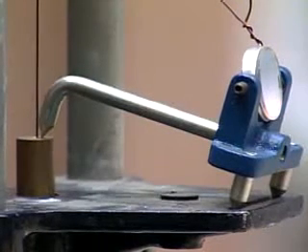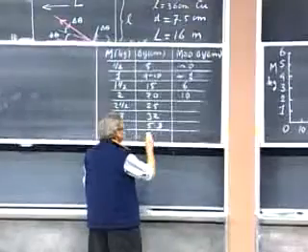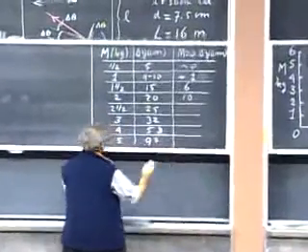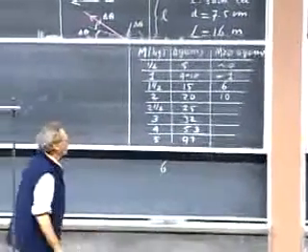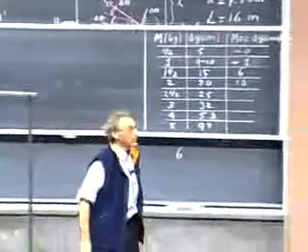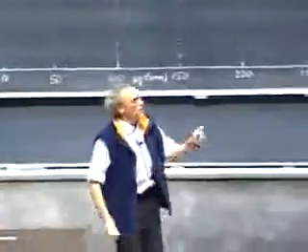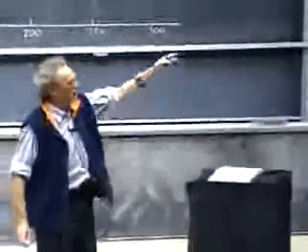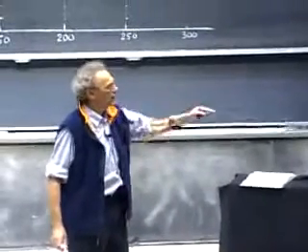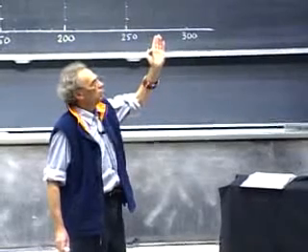Now you're clearly in that plastic flow portion. By adding 1 kilogram, look where that point is. It's still moving. What was 5? 97? So we're now at 6 kilograms. Oh, well, actually, that is still easy for me to estimate. I would say it's about double the length of that stick that we have on the wall, and the stick is 2 meters long. Is it moving? Yeah, it's still moving a little bit. It's a little more than 4 meters. Close enough, 4 meters, just for the idea, so it's 400.